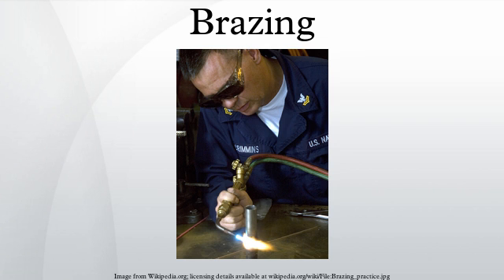Interaction with base metals. For successful wetting, the base metal has to be at least partially soluble in at least one component of the brazing alloy. The molten alloy therefore tends to attack the base metal and dissolve it, slightly changing its composition in the process. The composition change is reflected in the change of the alloy's melting point and the corresponding change of fluidity.